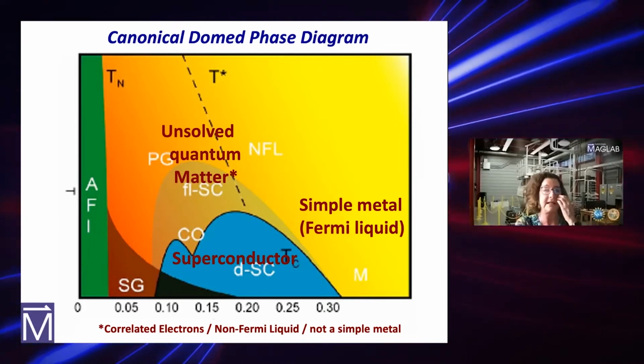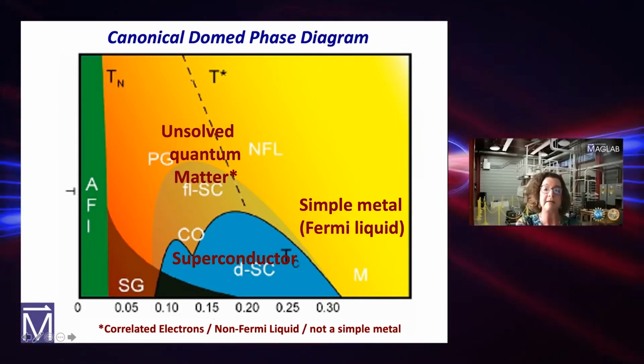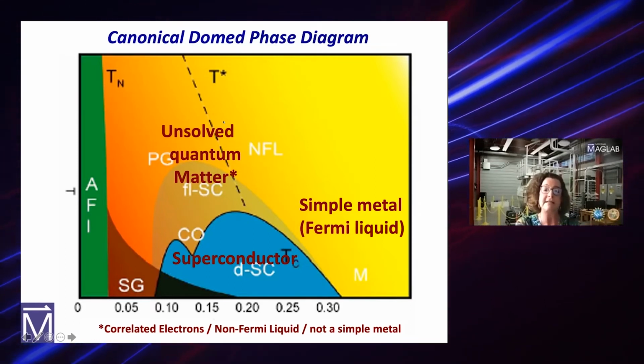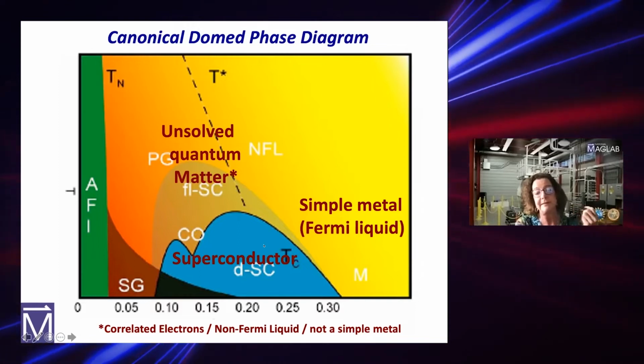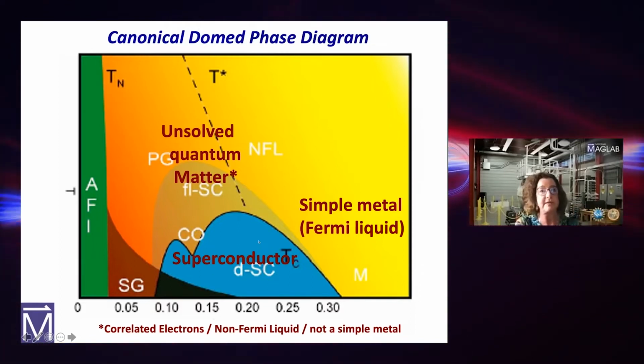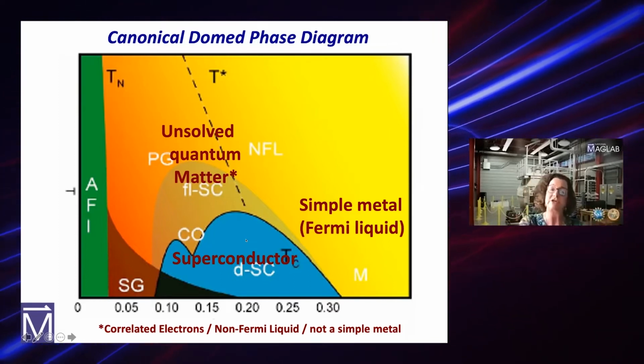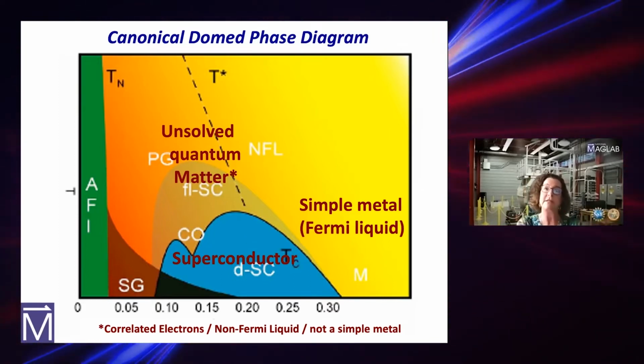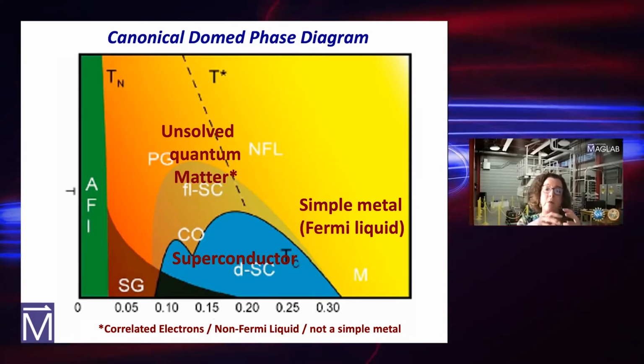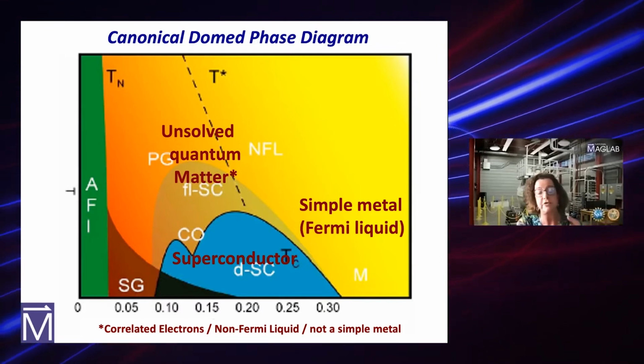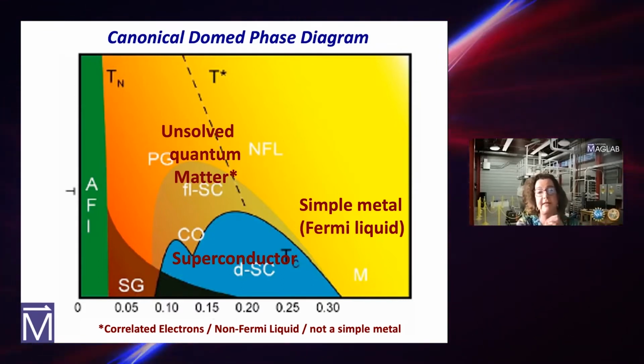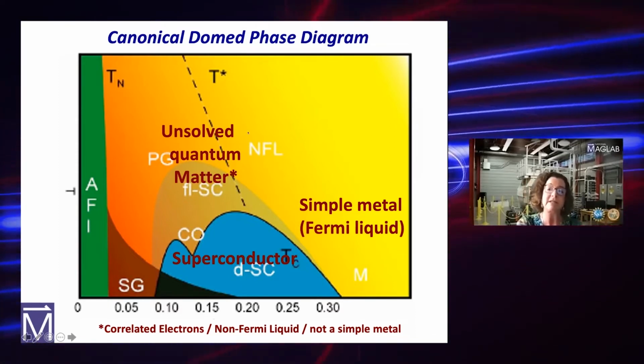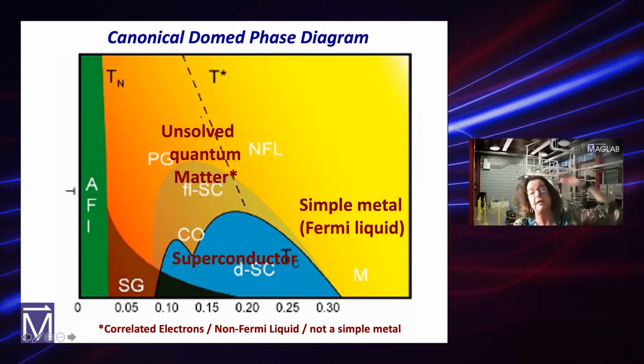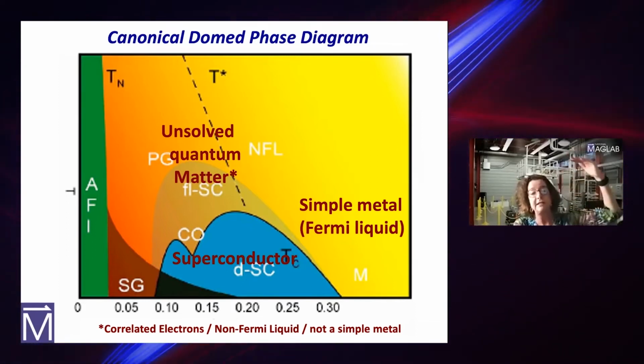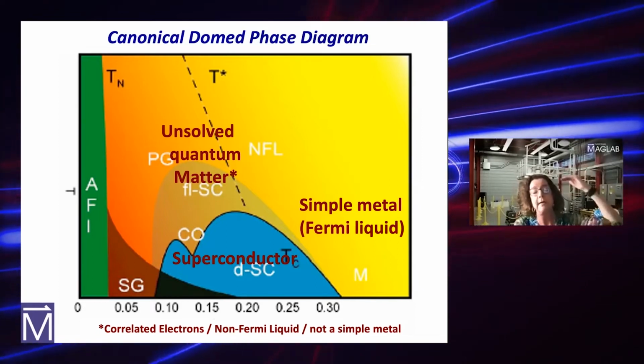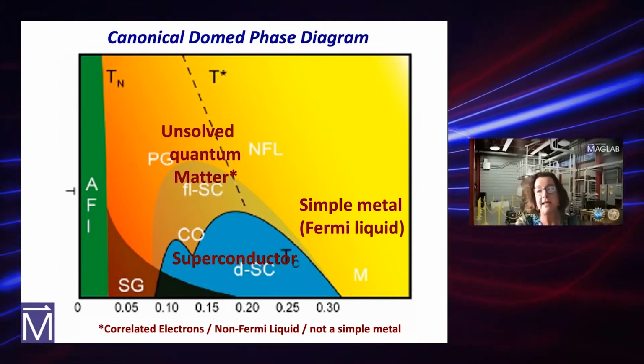So my definition is that we are finding unconventional superconductors, which is not necessarily because you don't always have it in unconventional superconductors; you can have S plus minus. The old definition of unconventional superconductors was that the superconducting phase, the superconducting order parameter, had a lower symmetry than the underlying lattice. That's not necessarily the case, for instance, in S plus minus. But in all these materials at some temperature, we find that the electronic fluid above the temperature of the superconducting phase breaks the symmetry of the underlying lattice, for instance, in the case of the nematic phases.